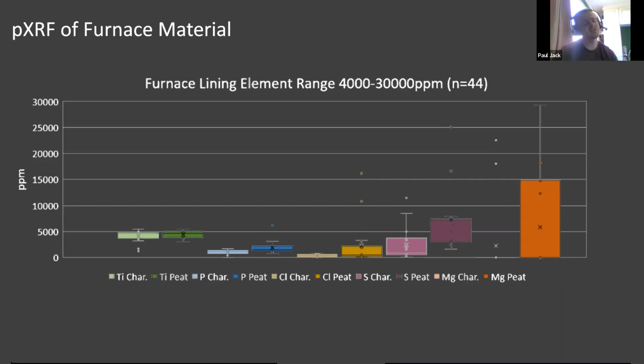And that's hugely significant because that means we could take a PXRF reading, which is quite a rapid, quite a cheap, quite a simple way of taking readings of the chemical composition of things. We could apply that to furnace material that's in museums or that's actually still out in the field. And we could then apply that using the statistical model and figure out what types of fuels furnaces were being exposed to in the past.